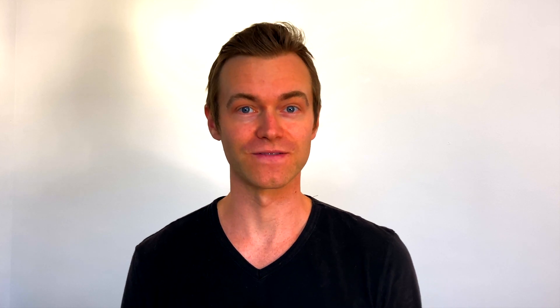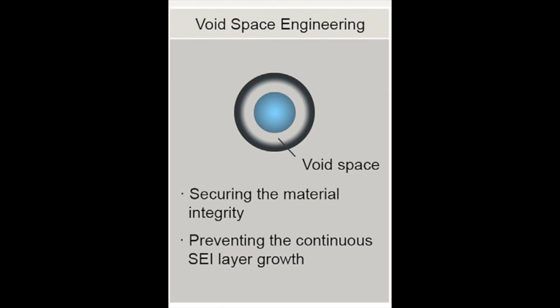Overall, bringing high-loading silicon batteries to the commercial market is extremely difficult. Another major consideration, if all the major issues are to be addressed, is the underlying expansion and contraction of the battery cell using a high loading of silicon. This would put use limits on the cell, and it's likely that void space would need to be placed inside the cells, which would prevent volumetrically dense cells from being produced.